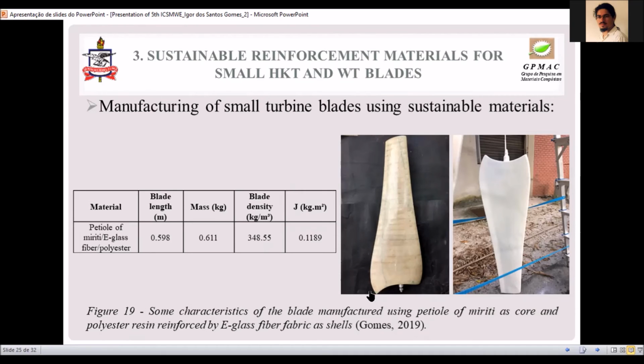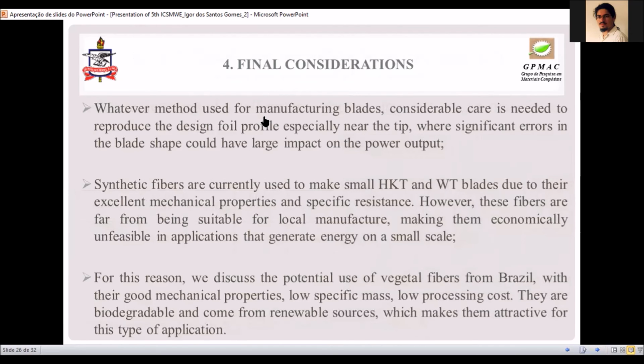Here we see the blade after manufacture, and here we see the blade painted. And in this table, we see that using petiole of miriti as a core, the manufactured blade has low mass and low density, and consequently a low rotational moment of inertia, which is the key element for the starting performance of a turbine. Well, a final consideration: whatever method you use for manufacturing blades, considerable care is needed to reproduce the design foil profile, especially near the tip, where significant errors in the blade shape could have a large impact on the power output.